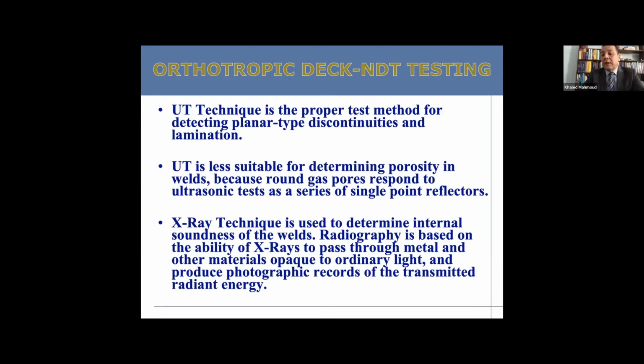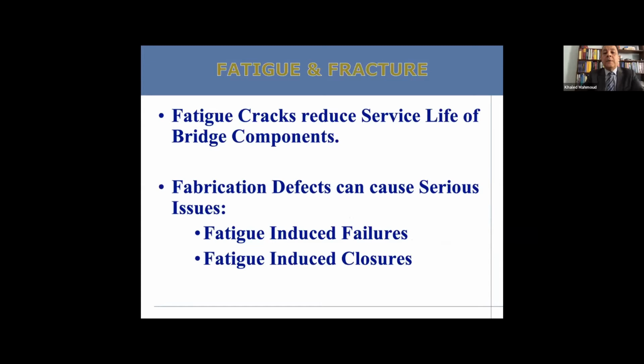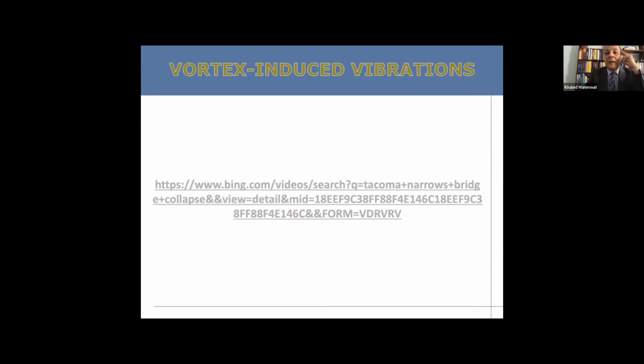And that, of course, is a very unpleasant situation. I can imagine the square meters of a bridge deck that suffers from this kind of crack. It becomes a very, very troubling issue. These fatigue failures, if they happen, where part of the bridge deck starts giving in to these cracks, can lead to closures, neither of which is desirable, to speak of longevity and good maintenance.